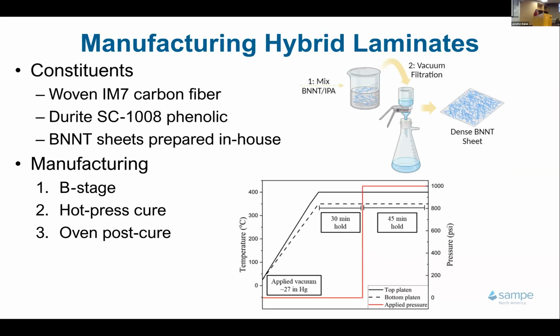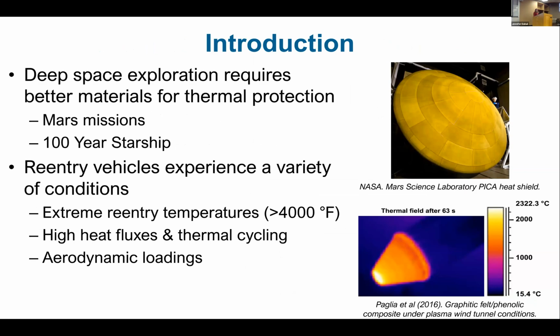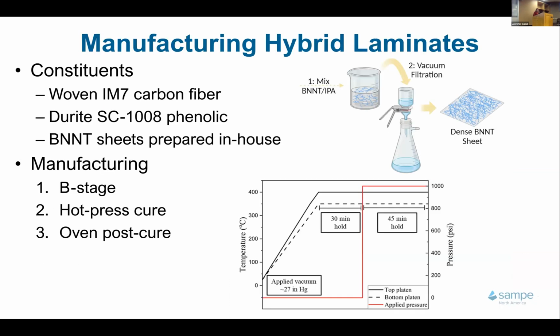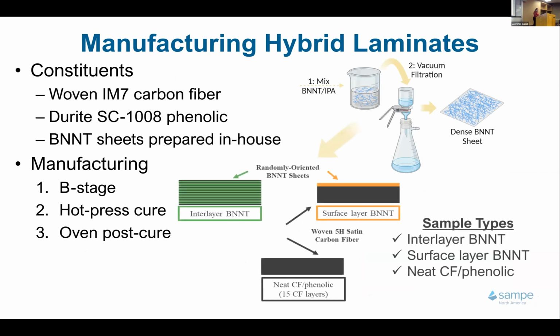So we need to look at the aerodynamic loadings and the high heat fluxes. We did pretty much the exact same processing parameters, but this time we're using a phenolic resin rather than a toughened epoxy. We're using the Durite SC-1008 phenolic resin. Otherwise, we are using a woven IM7 and BNNT sheets prepared the exact same way in-house. These are the manufacturing parameters. We also have surface layer BNNT and interlayer BNNT, which you saw as well. So you have the ones on the interply and surface layer, and then you have neat ones without any BNNT.